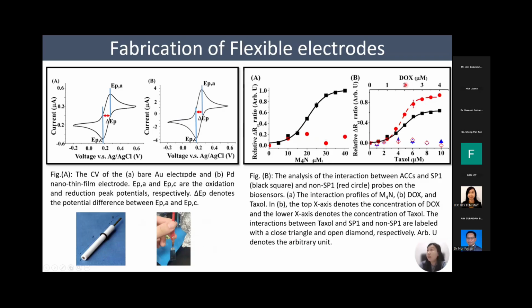We also continue using this palladium nano thin film to detect DNA-based anti-cancer compounds such as doxorubicin, M4N, and also Taxol. In this interaction we are using the ferrocyanide solution, and we only use 1 microliter of anti-cancer compound, and we can get the reading within 11 minutes, and the sensitivity can go down to 0.1 micromolar as detected by the EIS spectrum. You can see here. So we believe that this highly reactive surface of this working electrode can also be used in other kinds of biomedical applications.